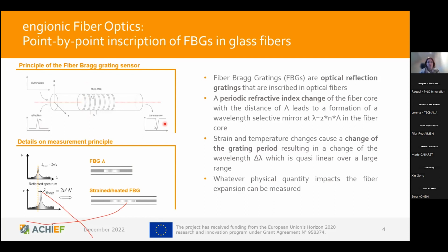And this behavior of the optical fibers changes if you add some physical properties to its environment. So you could either heat it up or stretch it. This affects the periodicity, so the distance between the periodic index modulations, and that then results in a shift in this Bragg wavelength that gets reflected. So whatever physical quantity impacts the expansion of the fiber, or as is the case for temperature, also has an impact directly on the refractive index of the material, can then be detected in this wavelength shift.